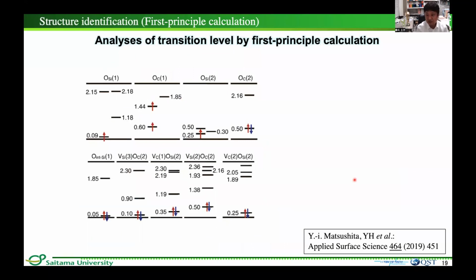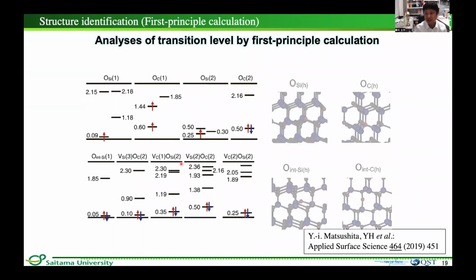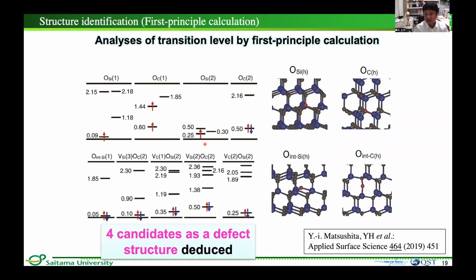We also attempted analysis of transition level by performing first principle calculations. We assumed some complex defects, including oxygen, like this. As a result, the candidates for defect structures were successfully limited to these 4 types.